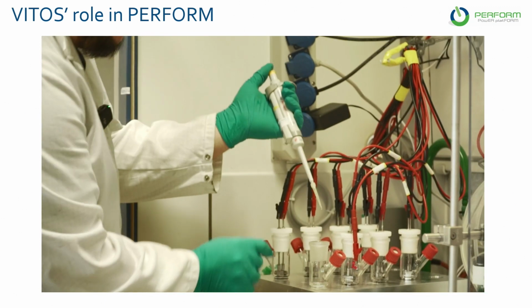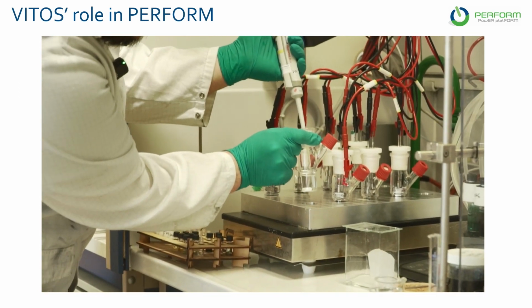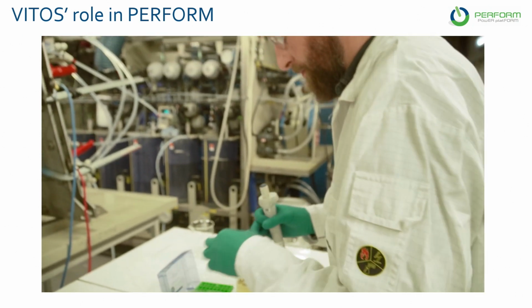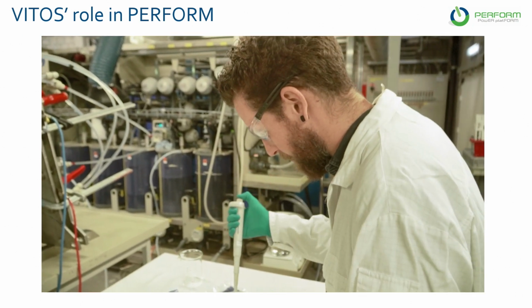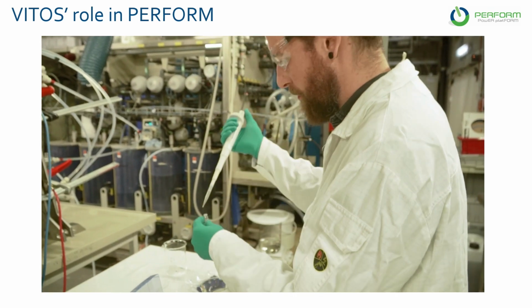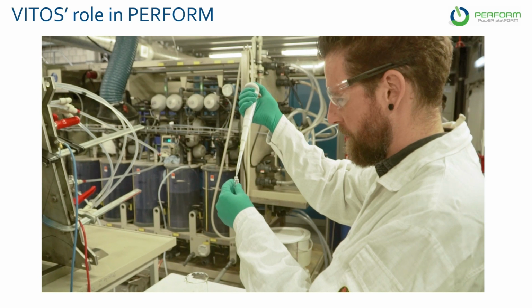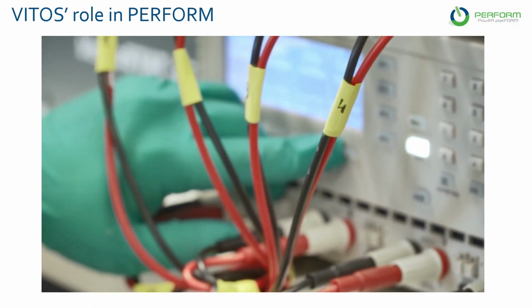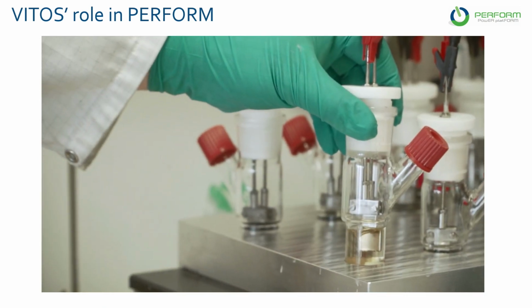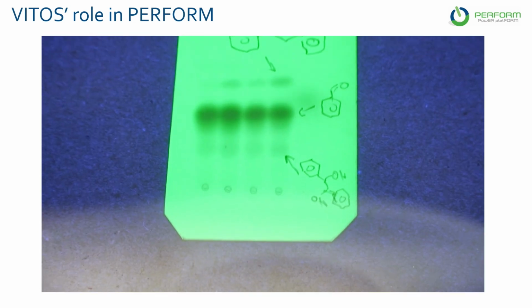To further increase the separation efficiency, we add another anti-solvent, we call it. Actually, it's a solvent that is used to lower the solubility of the glucaric acid in this mixture, which further increases the productivity of this separation. All these crystals can then be collected from the different process steps, and they can be further purified by using this anti-solvent to wash them. And all the washing liquid basically, which contains water but also the anti-solvent, can be recovered by distillation in a subsequent step.